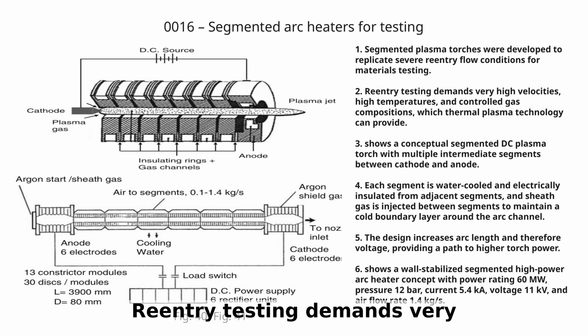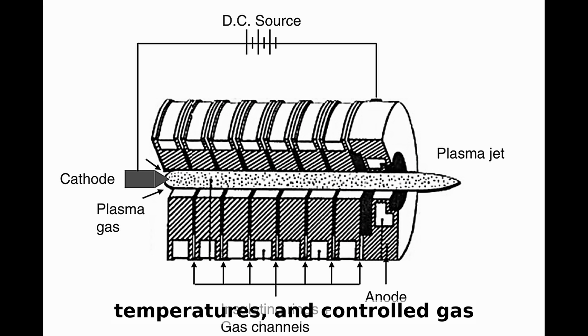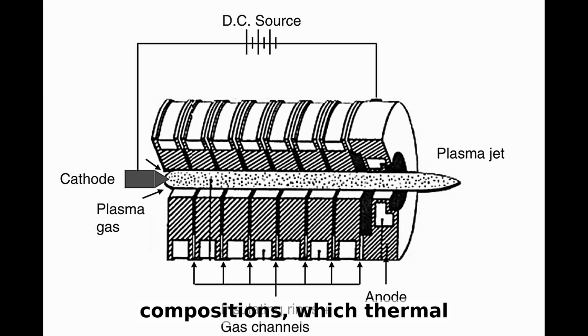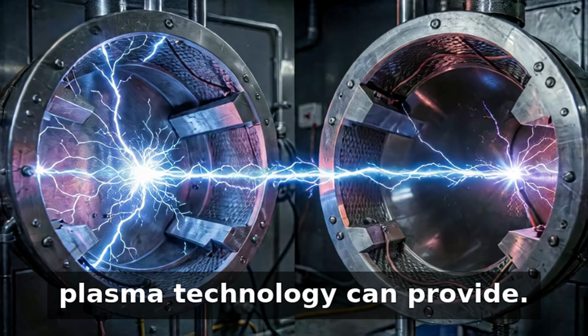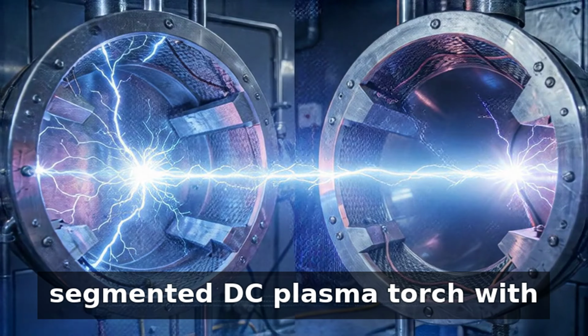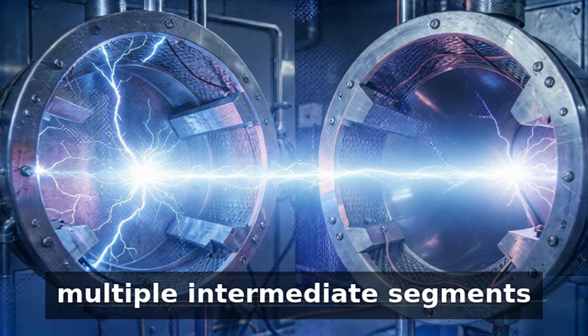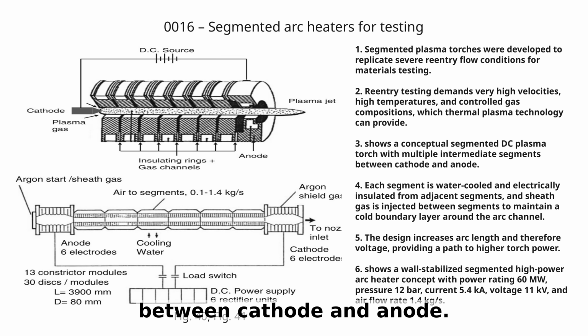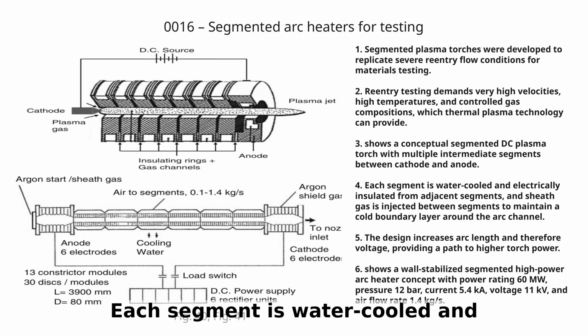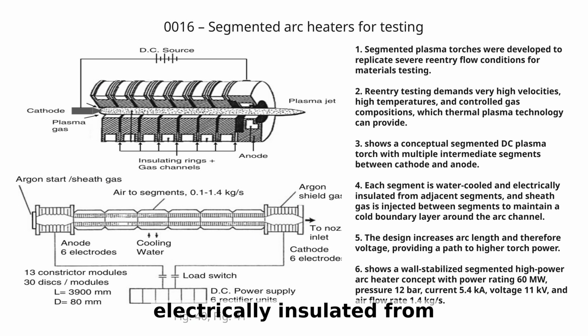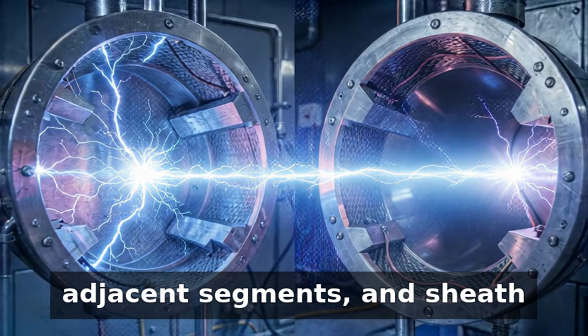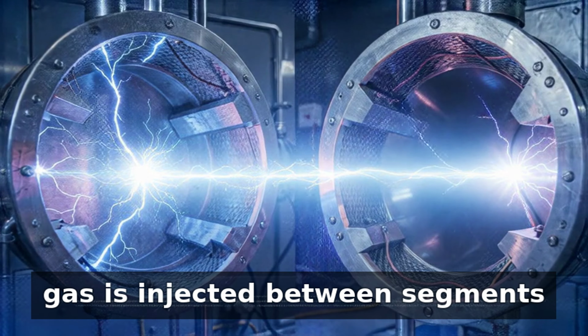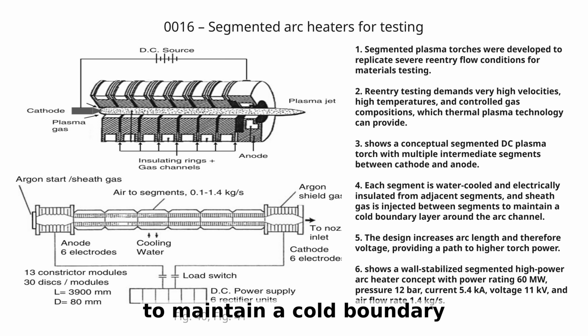Reentry testing demands very high velocities, high temperatures, and controlled gas compositions, which thermal plasma technology can provide. Figure 40 shows a conceptual segmented plasma torch with multiple intermediate segments between cathode and anode. Each segment is water-cooled and electrically insulated from adjacent segments, and sheath gas is injected between segments to maintain a cold boundary layer around the arc channel.